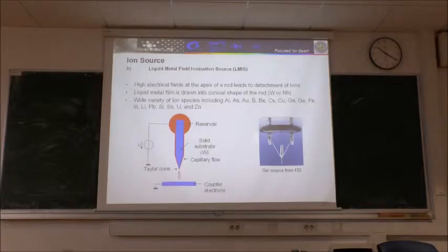So the ion source, we have to produce ions. Those ions should have relatively high energy, so it should be heavy. And normally, nowadays, gallium is used. Why gallium? Because gallium is a funny metal. It has melting point very low. Something around, I think, 30 degrees centigrade. So you need really small amount of energy to make it liquid.